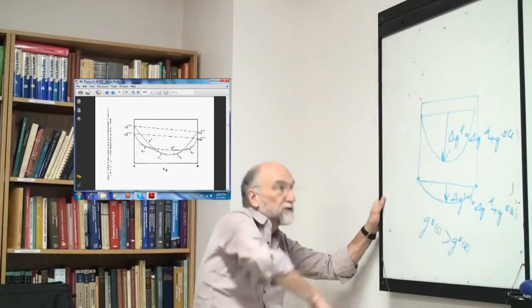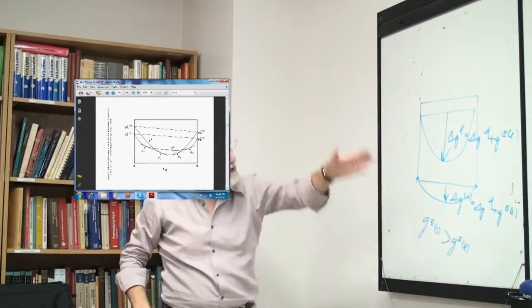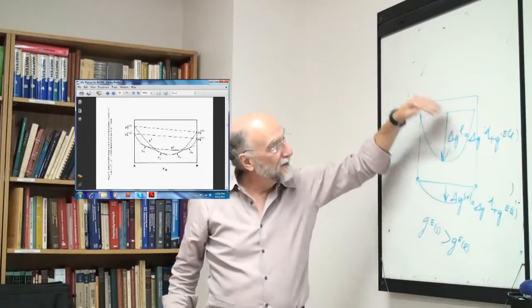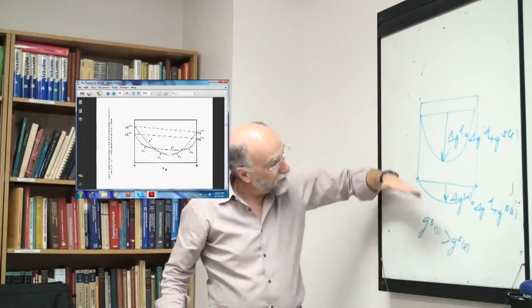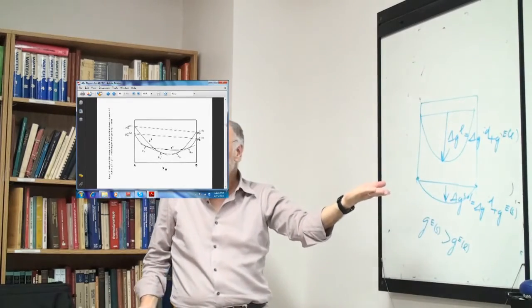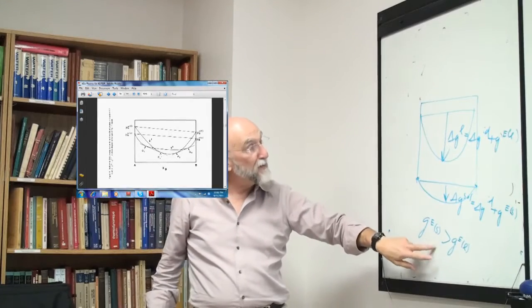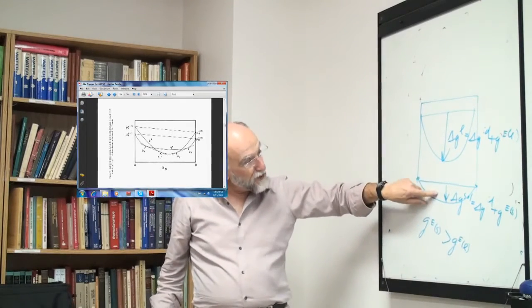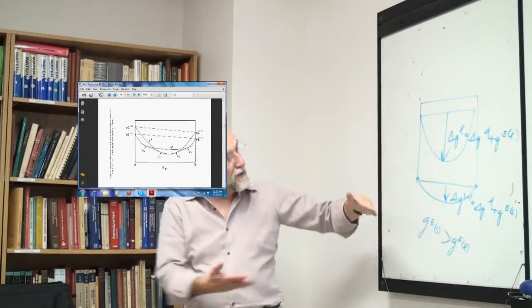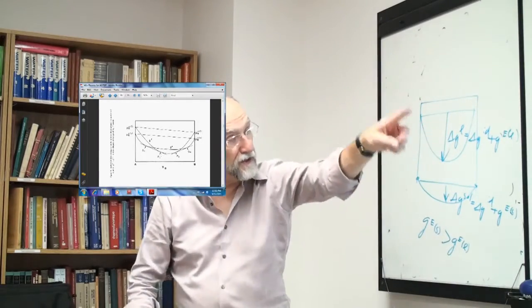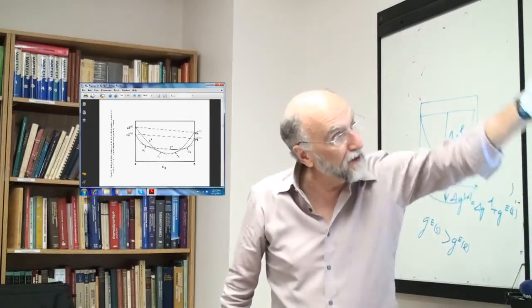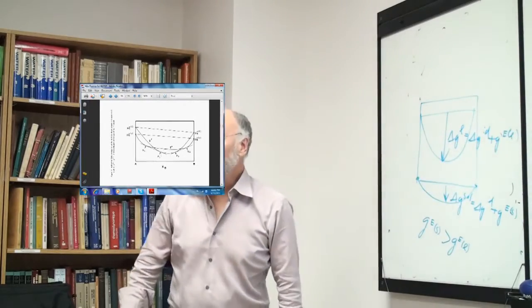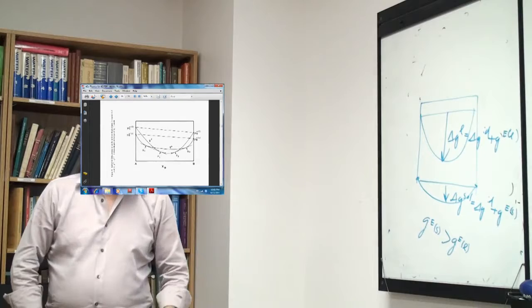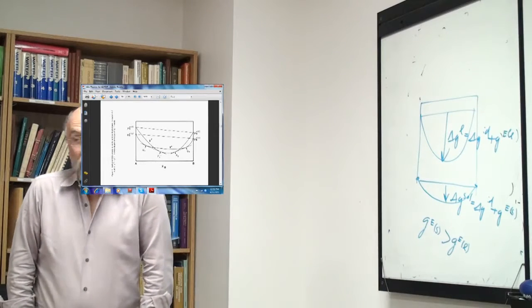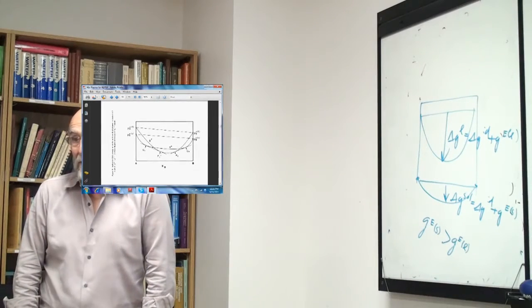So the liquid curve goes down more steeply, it's more stable relative to the ideal. This is negative here, in this case. In this case you consider this to be positive, which makes the phase less stable. Okay, so the fact of mixing destabilizes the solid relative to the liquid. So there will be a temperature when the phases intersect, as they do here. The solid curve is flatter than the liquid curve, which means the solid is destabilized relative to the liquid because of the mixing.